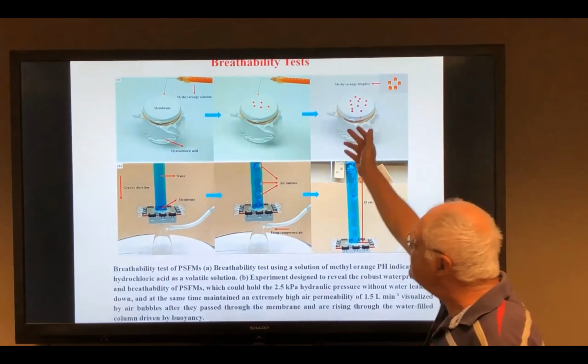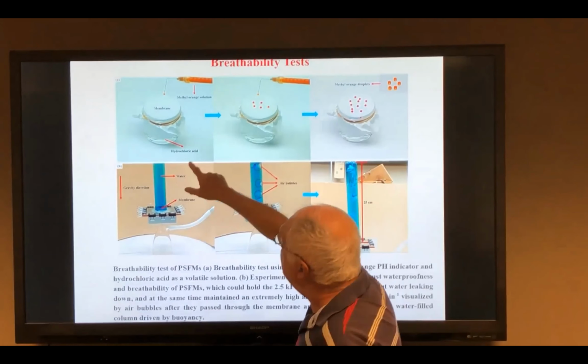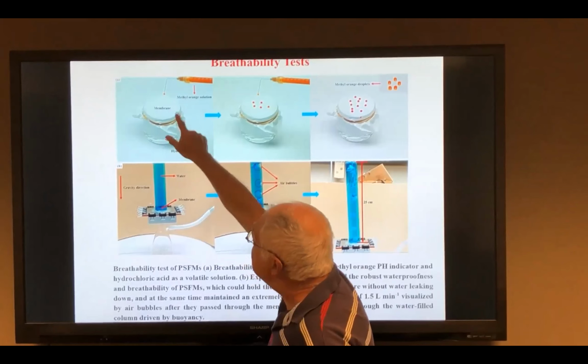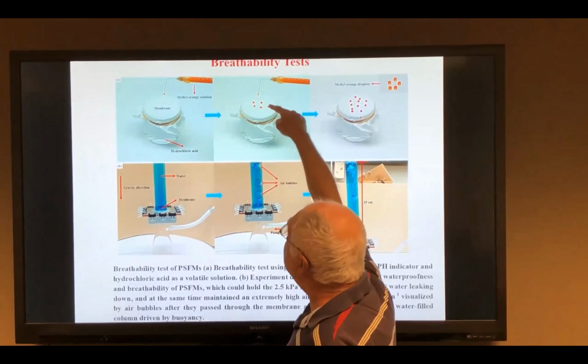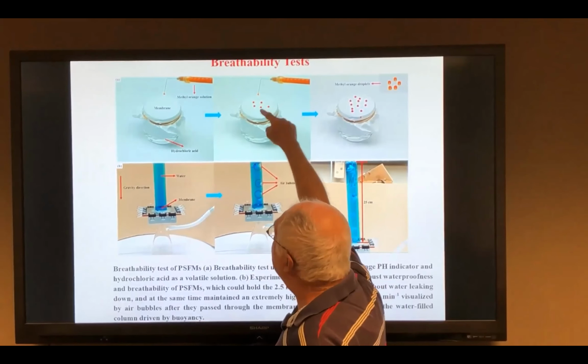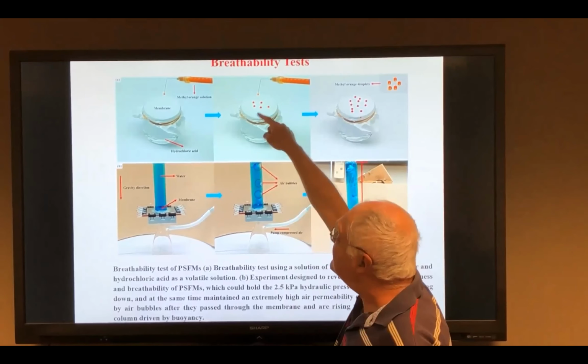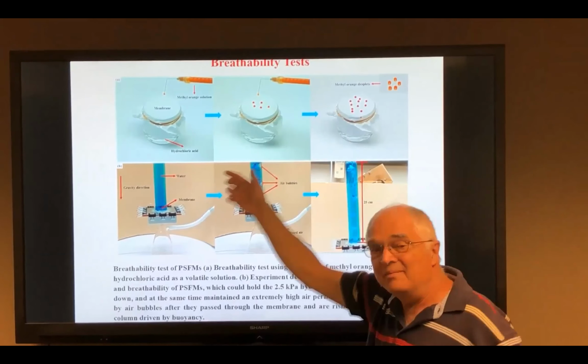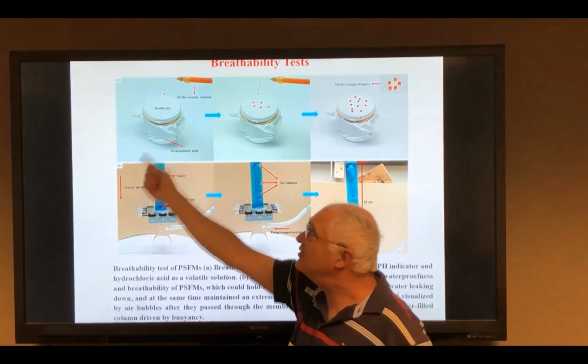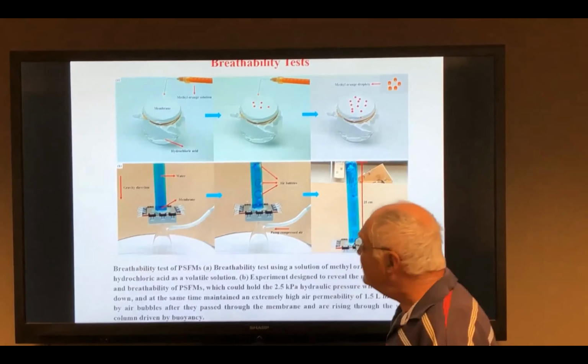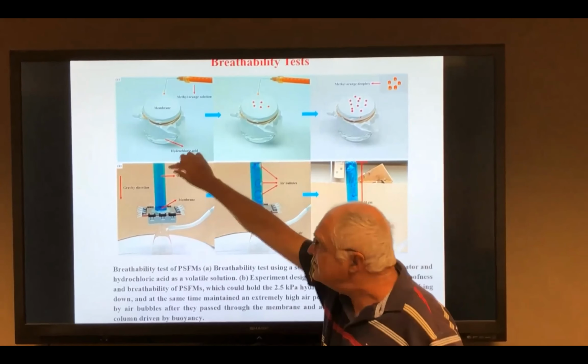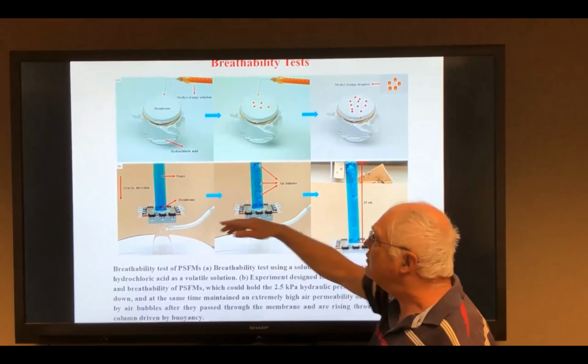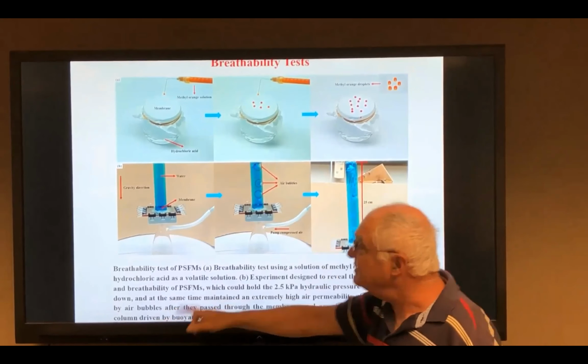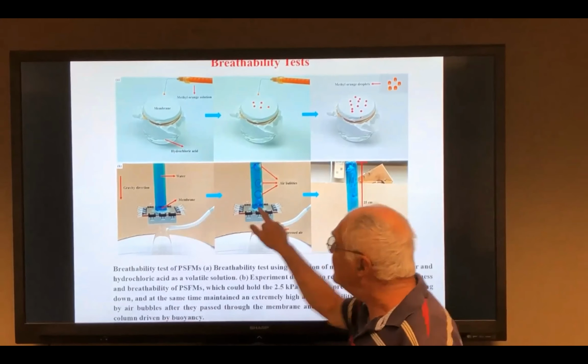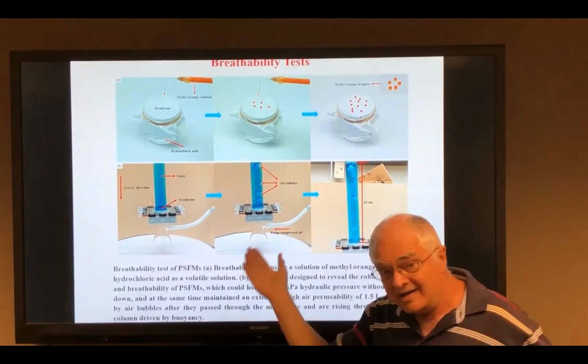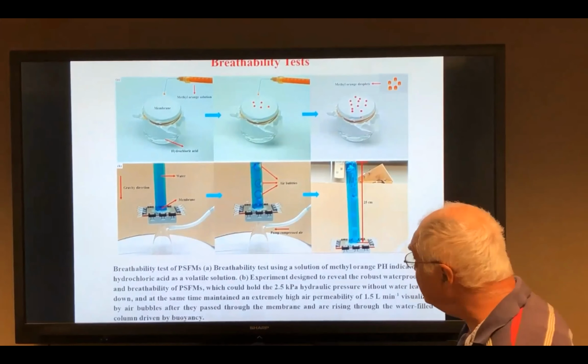So this is one of the experiments, when hydrochloric acid evaporates through the membrane, and the marker, like a litmus paper, is located on top, and the marker changes color. So that's a manifestation of penetration of vapor through the membrane. In other cases here, water is in the pipe, the membrane is under, water is not going through this membrane, okay? However, gas is supplied here, and gas bubbles go through. So once again, penetrability, breathability is proven here.